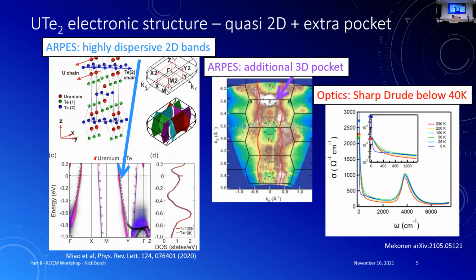All right. And then electronic structure. What I'm showing you here is actually just DFT for the thorium compound. If you ignore f electrons, it's supposed to look like rectangular Fermi surfaces. Angle-resolved photoemission actually shows you this on high energy scales. So you've got these very dispersive bands that cross the chemical potential. By the way, if there are questions, I would much rather you raise your hand. If I'm paying attention, I'll choose you. I don't want to wait until the end and then forget what I said.